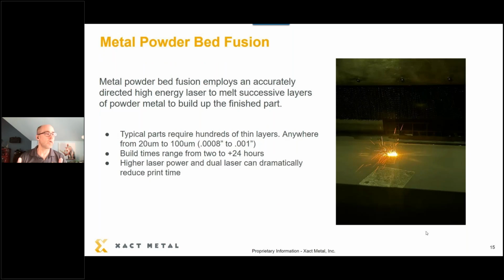Now, I do want to talk about what our technology is. It is laser powder bed fusion. Metal powder bed fusion, laser powder bed fusion, DMLS, everybody's got all these different terminologies depending on what company you work for. But basically, we're laying down powder in layers of anywhere from 20 microns to 100 microns thick. For those not familiar with microns, it's about 1 thou to about 4 thou thick layers. And then we come in with a galvanometer and laser weld all that powder together. Pretty simple, right? In a sense, it's a laser welder. We're welding powder. Build times range from 2 hours to 24 hours. And you can do single laser, dual laser, and I'll cover some of that in a minute.